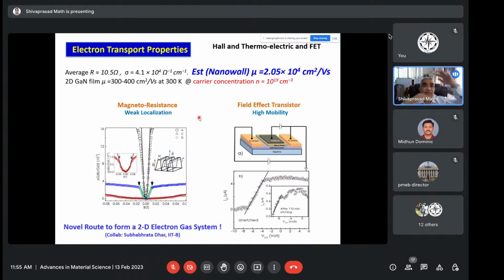So that means I have an insulator-like material which gives me semiconductor-like light, plus it's also a conductor. The same material behaving as an insulator, semiconductor, and metal was very, very surprising for us. So we did some low temperature studies and understood the phenomena that there is weak localization in these materials. And that means it is giving evidence for a 2D electron gas in this material. 2D electron gas is an amazing system to study. And this also seems to show even at room temperature, which was a bit surprising.